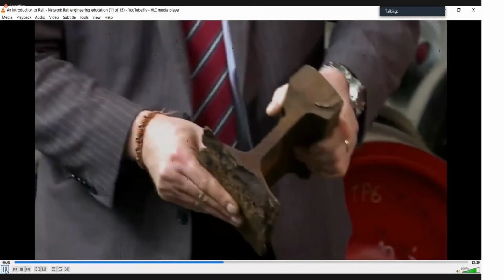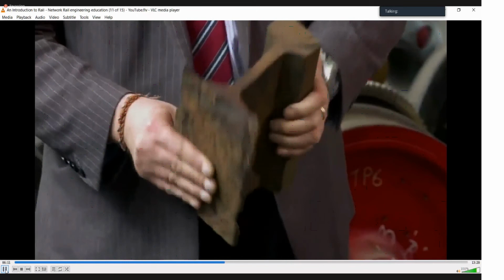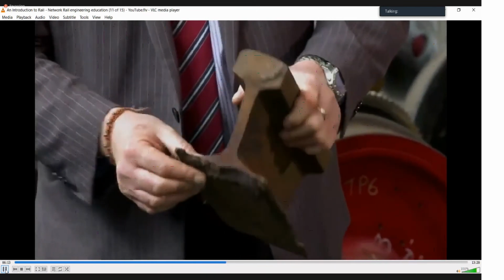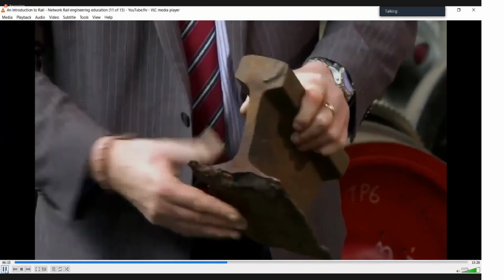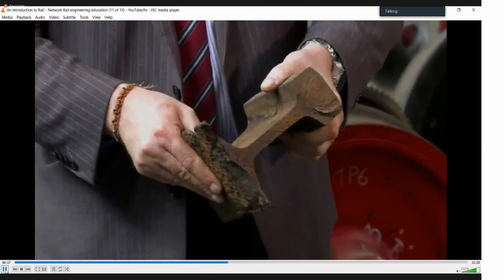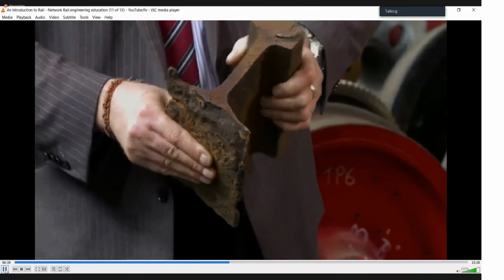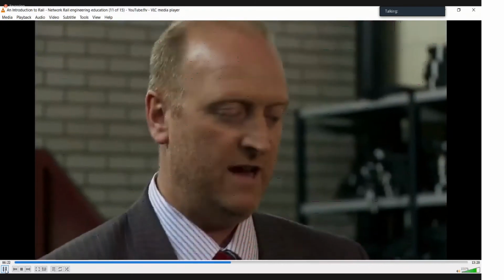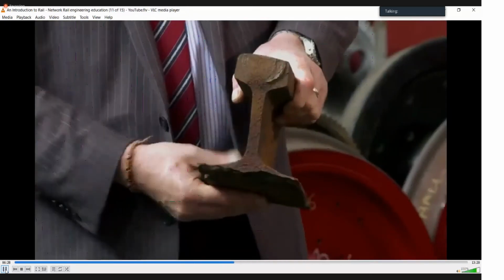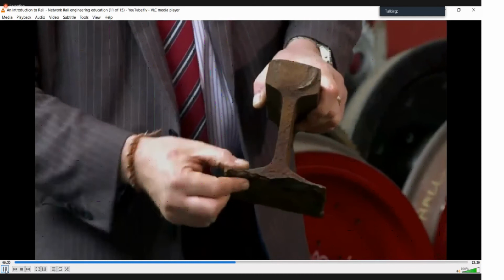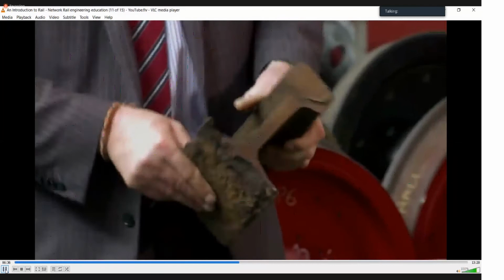Here we have an example of a rail removed from an aggressive environment where the foot of the rail is corroded away, a large amount of material has been lost. This will result in rail failure if the rail is not removed in good time. Aggressive areas are where we would have exposure to water or perhaps the sea or salt water. Level crossings are particularly bad where we have a lot of water from the road, and also during winter salt is applied to the road which causes a significant increase in the rate of corrosion in those locations.